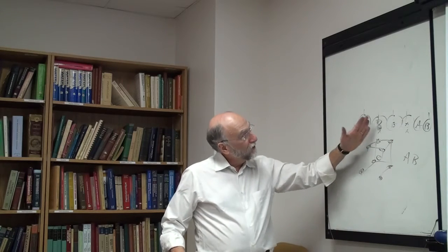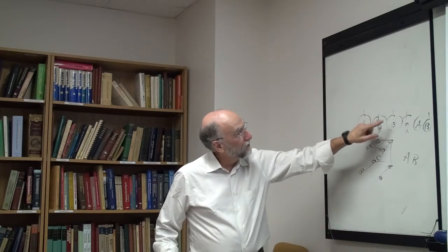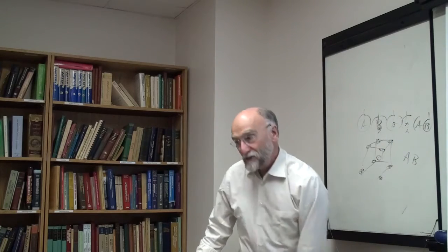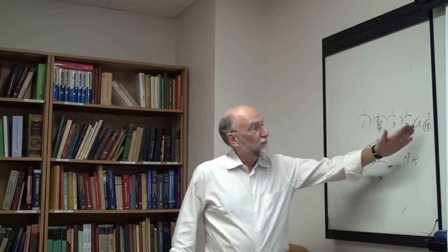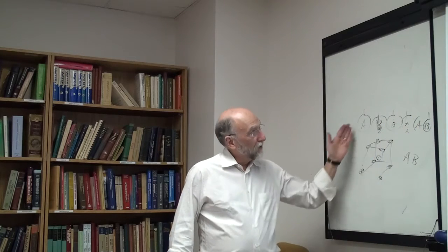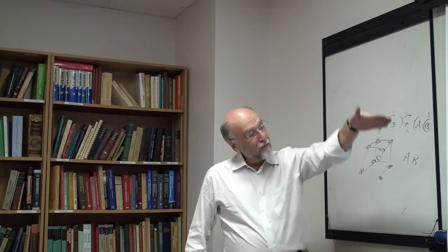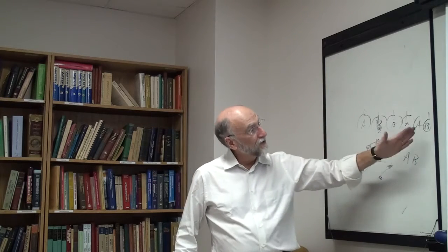But still, if you go an even number of lattice sites, you go 2, 4, 6, 8, 1 million, 1 million and 2, the probability is still greater than 50% that that's going to be occupied by a B. You get my point? So it's fundamentally totally different. So you can have almost complete disorder, but still it's long range ordered. Even though the system isn't very ordered, it's still long range. It's 2 sublattices. You go on 1 million lattice sites because that's an even number. The chances are greater than 50-50 that it's going to be occupied.